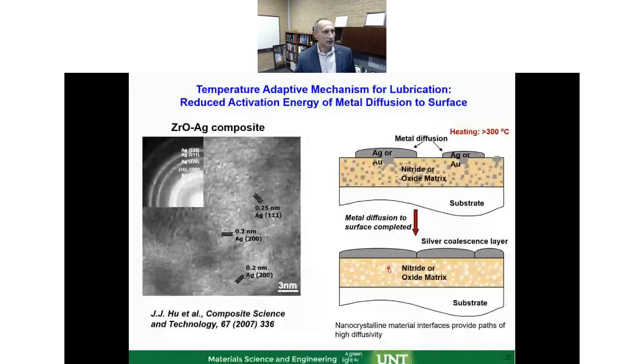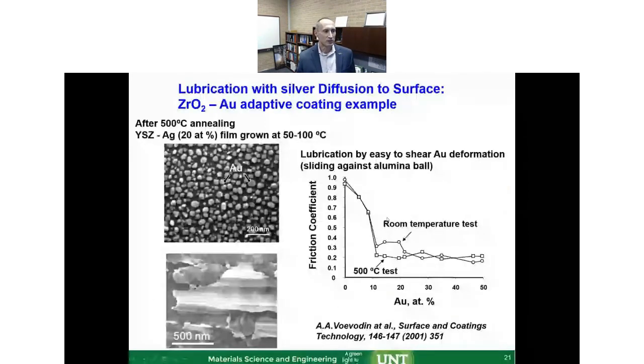And once you heat it, they are driven by surface energy minimization out of these oxides to the surface, and they will coalesce on the surface. And now, because they're soft, and because the temperature is now more than 300 C, they are even more softened and provide good lubrication in that condition. So let me show you the examples here with zirconium oxide and gold, and pardon me, this here is the gold, this should be the silver. So you can see here the gold grains showing up on the surface, and they are smeared, of course, in the tribological track and provide this lubrication shown over here.